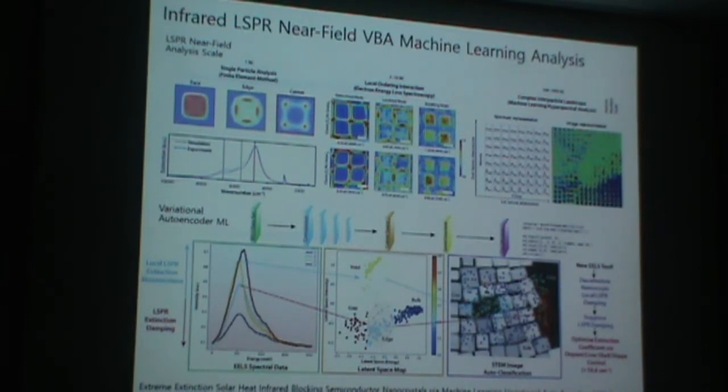So an outline of that would be using variational autoencoders to extract EELS spectra data in individual pixels, then mapping them out in latent space and auto-classifying them, using STEM EELS as reference. You can use auto-classification to automatically track down features such as voids, gaps, or edges of such complex nanocrystal structures in thin film nanocrystal structures.